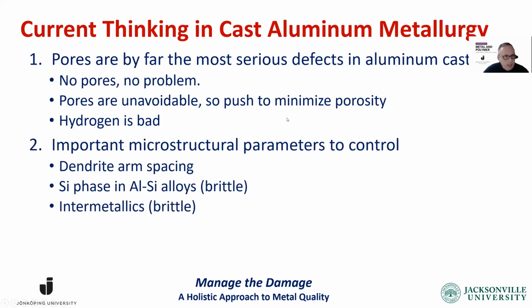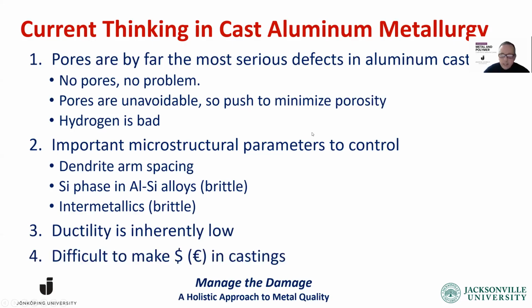Then there are important microstructural parameters to control only in aluminum castings, not in wrought alloys, but just in aluminum castings. The dendrite arm spacing comes to mind. Silicon phase in aluminum silicon alloys, because silicon is so brittle, and intermetallics like iron containing intermetallics, which are brittle, make the castings very brittle. Ductility is inherently low, much lower than in wrought alloys, although it's the same metal. And it's difficult to make money in castings.